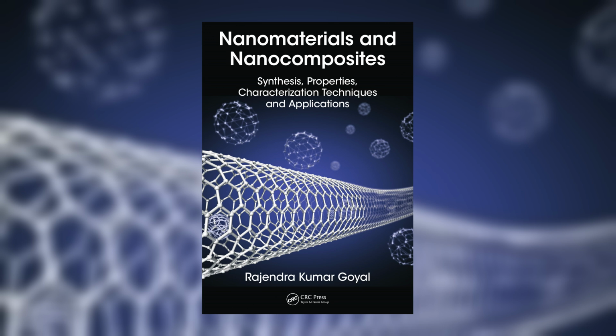This section explains why particle size takes over the properties of a nanomaterial once a crystal gets small enough. Shrink a crystal and one number takes over, the fraction of atoms sitting on a surface, which grows roughly as 1 over the diameter. Below about 10 nanometers, that fraction stops being negligible, so every property carrying a surface energy term begins to drift. Melting point falls first because surface atoms reach liquid-like mobility at lower activation energy. The same logic then propagates to mechanical, electrical, magnetic, optical, and catalytic behavior.